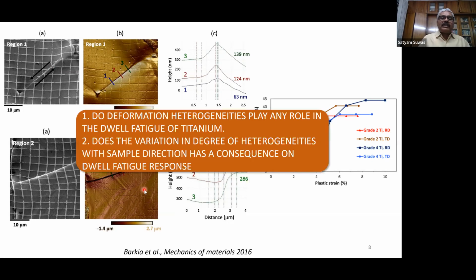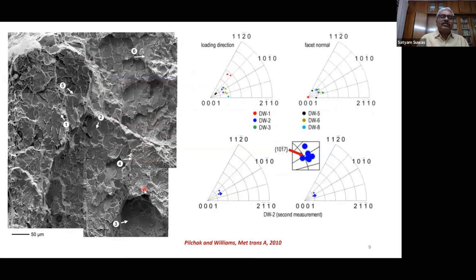So now the question is whether the deformation heterogeneities play any role in the dwell fatigue of titanium, because the heterogeneities we could see here very clearly. And also we wanted to examine whether this variation in the degree of heterogeneities with sample direction has a consequence on dwell fatigue response. So this was a very comprehensive work done by Adam Pilchak and Jim Williams, and they just examined the fractography of dwell fatigued samples, and they found that most of the grains where fatigue crack initiation has taken place are very close to basal, right?